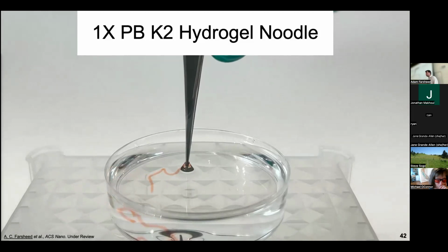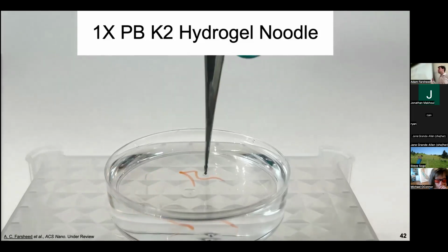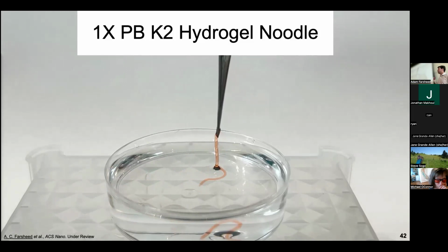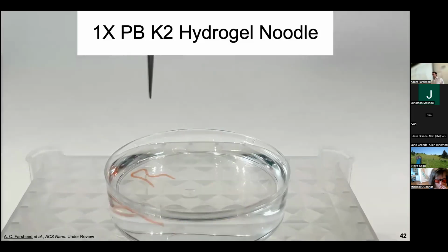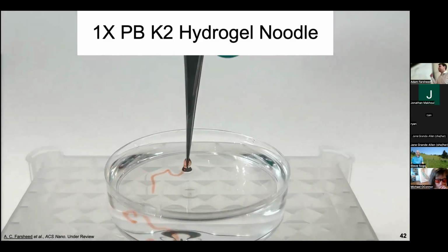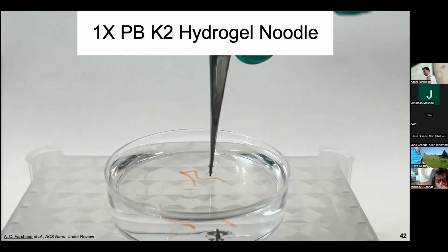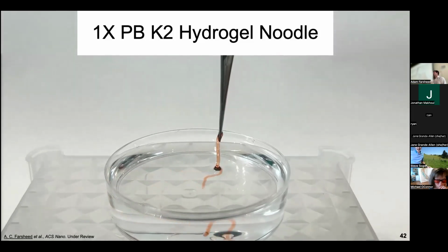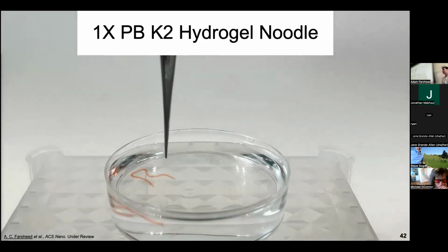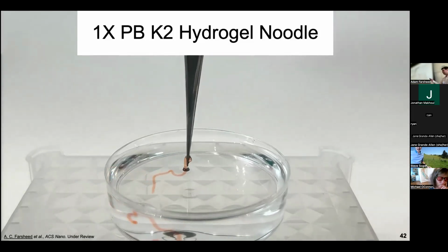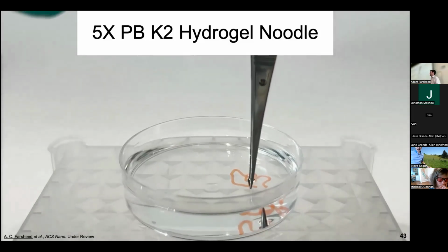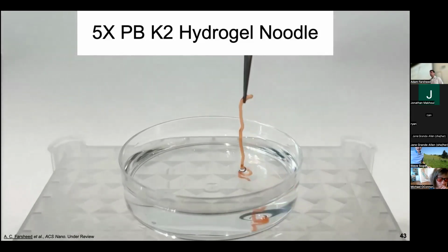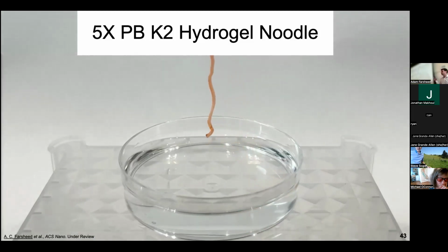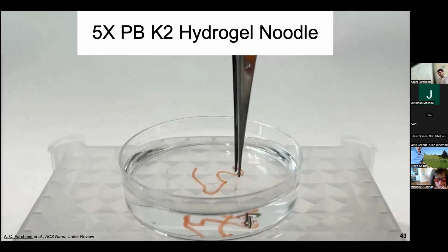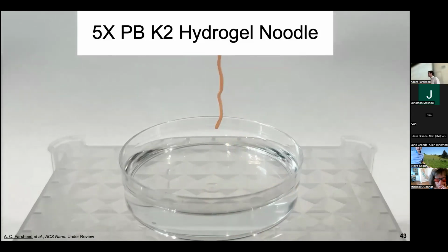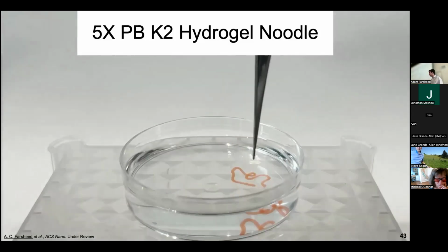Next, I'm going to switch over to the properties of these hydrogel noodles, starting with the 1xPB noodles. And what you may notice is that I'm trying to pull these up out of solution, but they're kind of trying to fight back against me and pull themselves back into solution. And what we're actually seeing is that the strength of these noodles is not enough to self-support over these long distances, and they're actually fracturing. Now, this is in stark contrast to the 5xPB noodles, where I'm able to easily pull them up out of solution. I'm able to drop them pretty aggressively, and they're able to maintain their shape. And I can repeat this over and over.